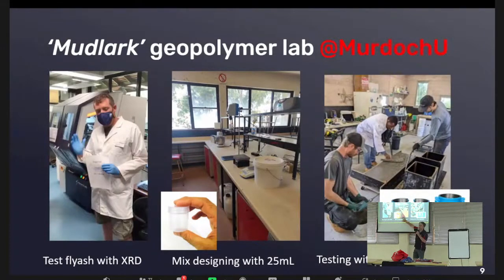And then what we've found now is the best way to develop the different mix designs is, in one laboratory, we just take small 25mL vials and develop geopolymer mixes in small test batches, and we can crush them quite easily to test them. And then once we think we have a good mix design from these small vials, we'll go down into what's probably our field laboratory, and we'll be pouring much larger 1 litre cylinder moulds, and other such moulds as well, and getting experience using the preferred mix design of the geopolymer. Okay, next one.